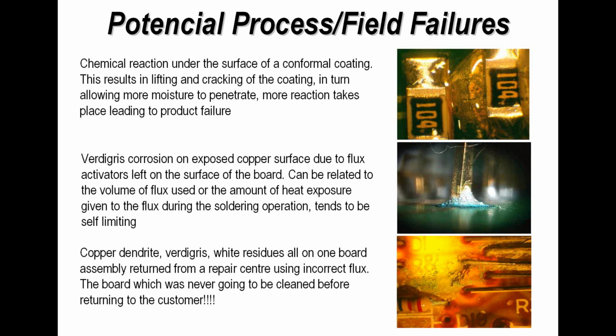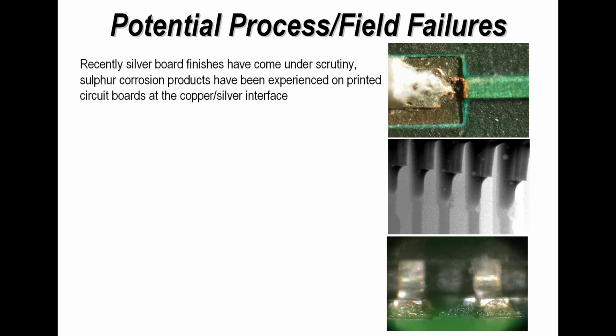So we've got white residues, we've got copper dendrites because of moisture and applied voltage, and corrosive materials and verdigris, all three in one place. One final thing I wanted to mention, and this is something that's come up recently in the last few years, where people have been using silver finished printed circuit boards. There's not a problem with using silver, but silver in combination with exposed copper in a sulfur environment can actually lead to corrosion.